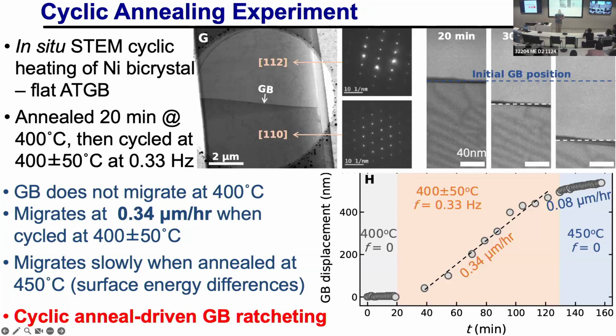I won't show you the following, but let me mention it. Colleagues also just took their bicrystal and put an electron beam right at the grain boundary and moved it back and forth, passing over the boundary many times. So it's not really thermal cycling because the thermal conductivity is quite high, so it's pretty much isothermal. But even so, and I don't know why this works, when they go back and forth many times, you still get some net migration in one direction. And if they increase the frequency, the migration rate goes up. I don't have much to say about that one, simply because I don't really know what the driving force is in that case. It could be defect fluxes or something like that. I don't know. I don't want to speculate too much.